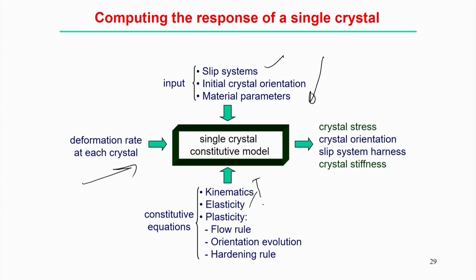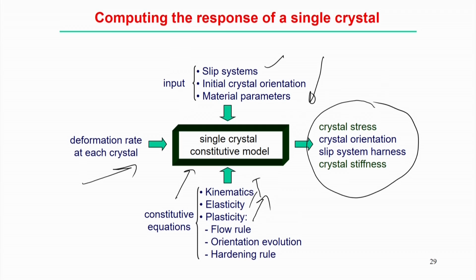Plasticity means plasticity of the single crystal structure in terms of the flow rule, hardening rule, and orientation evolution; all this constitutive information is linked. And finally we can predict the crystal stress, and the final prediction of the crystal orientation, slip system hardness, and crystal stiffness. Computationally, getting all this information to construct the single crystal constitutive models in terms of crystal stress, crystal orientation, slip system hardness, and crystal stiffness is really expensive, but it is necessary to model the deformation behavior of the single crystal structure.